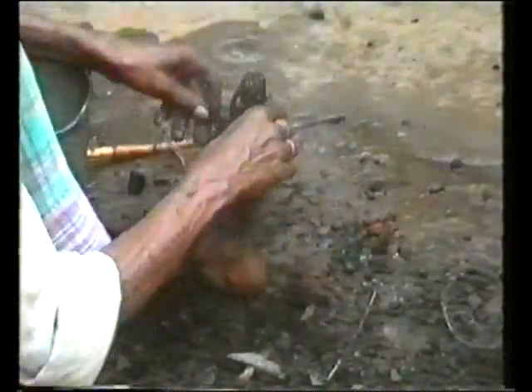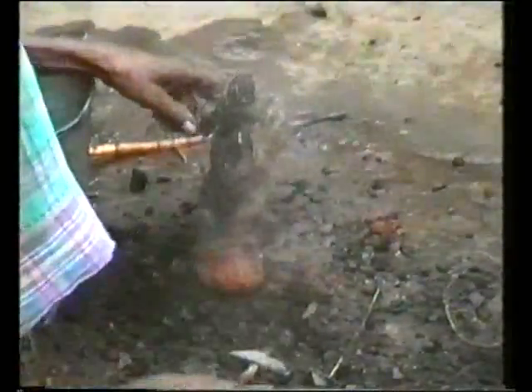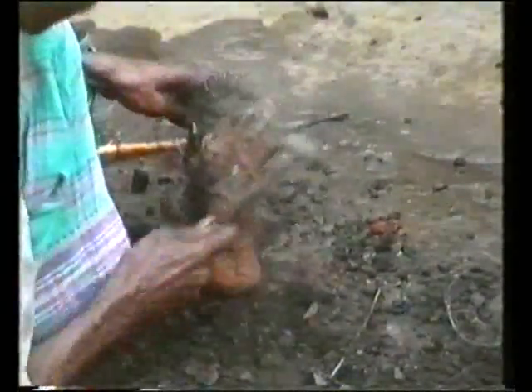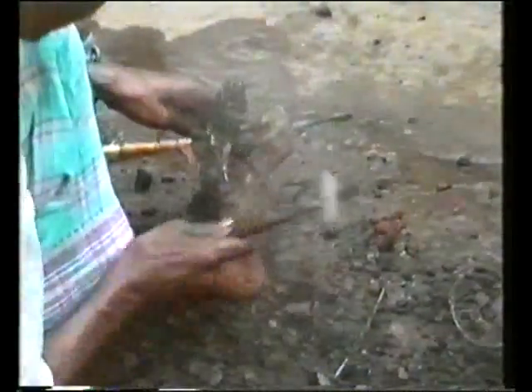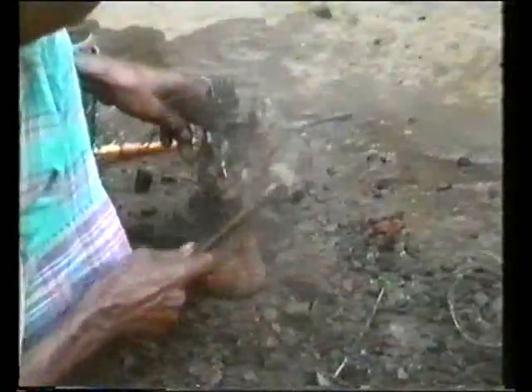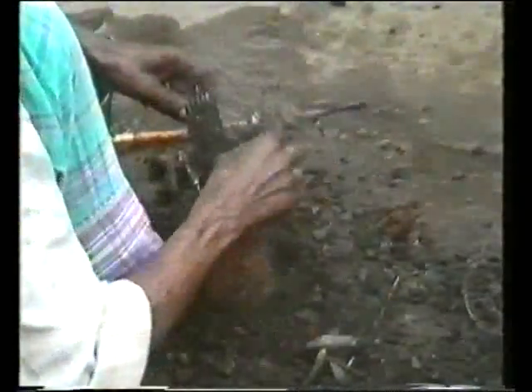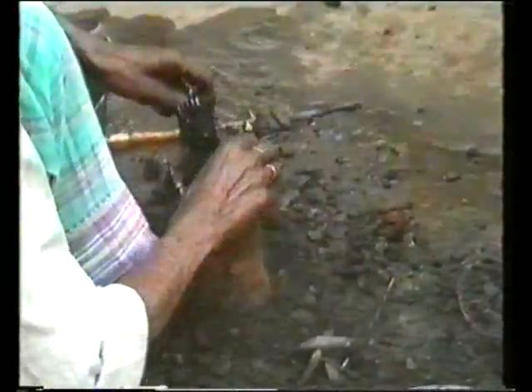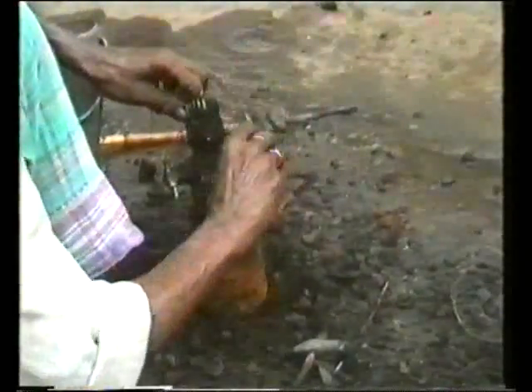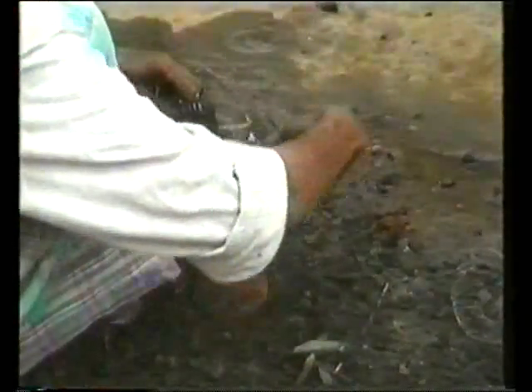Because only one metal feeding sprue has been used and no gas vents except for the hole in the crucible, there is very little work involved in the clean-up stage of this technique, which may partly compensate for the high failure rate. The figure is basically complete when it is removed from the investment.